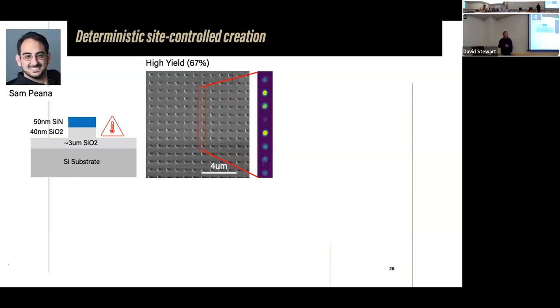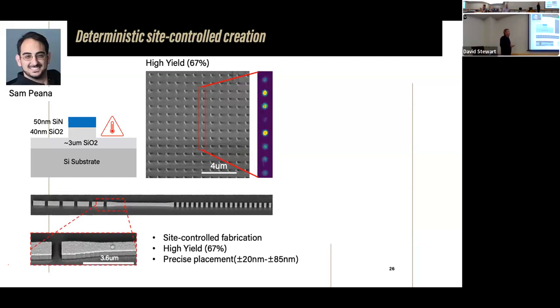And what was obtained, as you will see in a moment, is that if you choose a particular column like it's shown here, then actually 67% of these arbitrarily chosen have single photon emitters. So what we believe is happening here: the strain is right, and you create a single photon emitter. Then, as soon as it's created, the strain is released, and as a result, the second effect simply doesn't appear. As my colleague Evgeny Narimanov put it, strain blockade, because one effect already released the strain, and the second one simply doesn't appear. If it's really the correct understanding, then we probably would be able to, in a controllable way, bring the yield close to 100%.